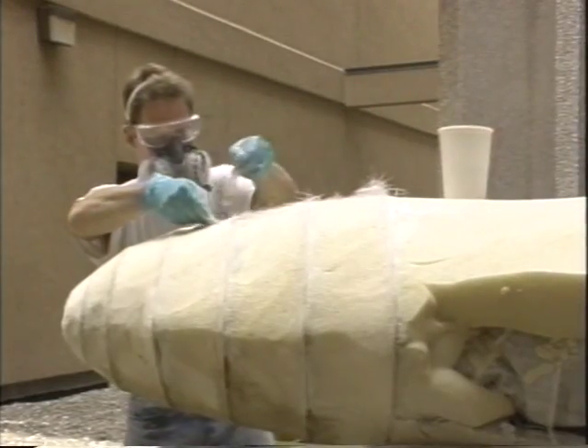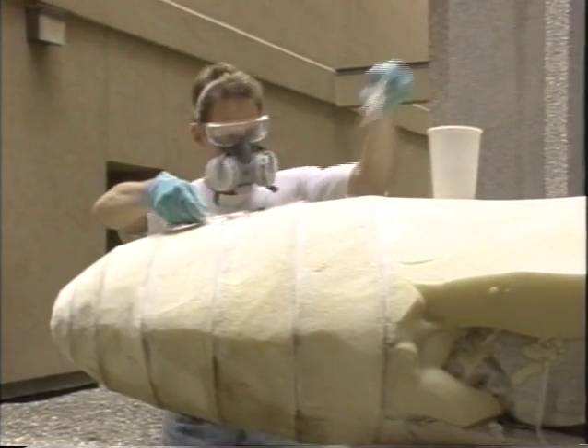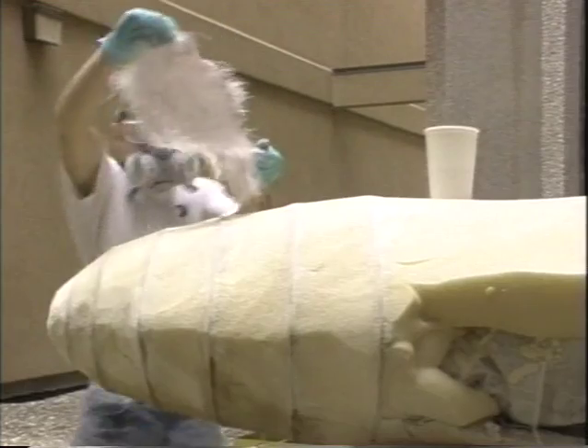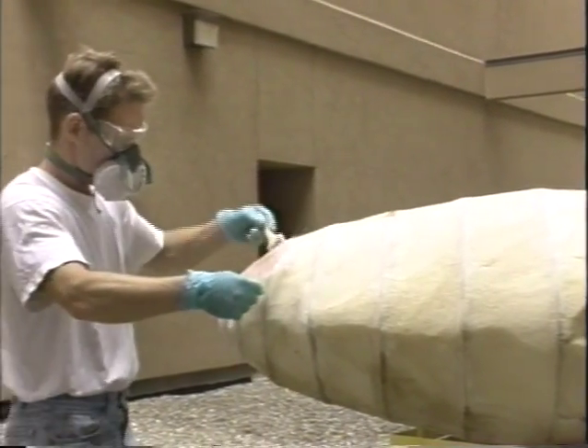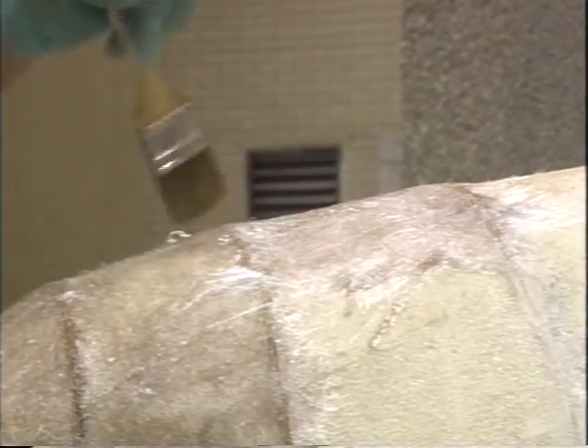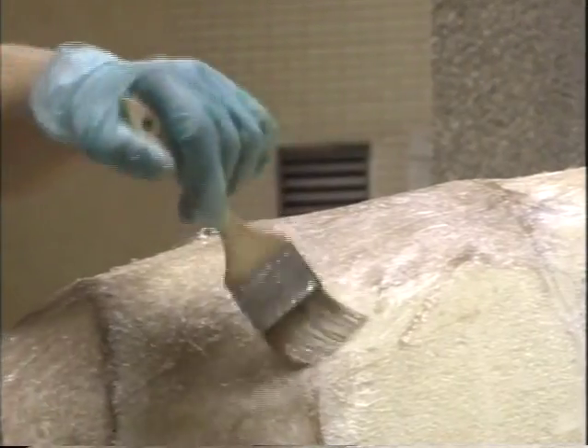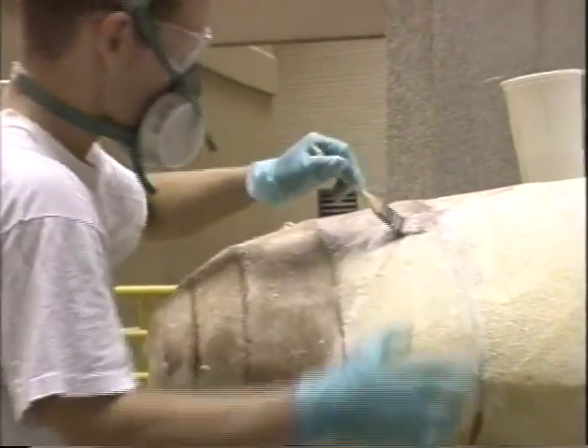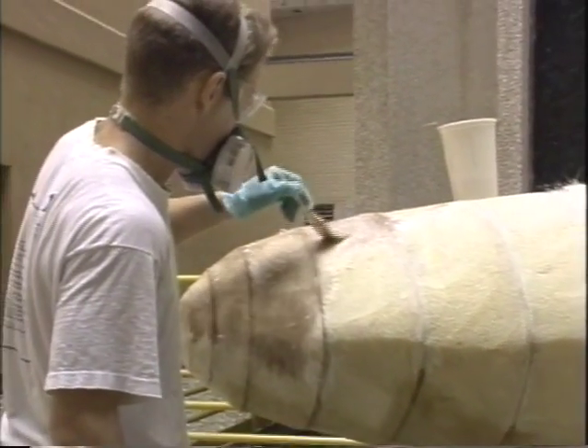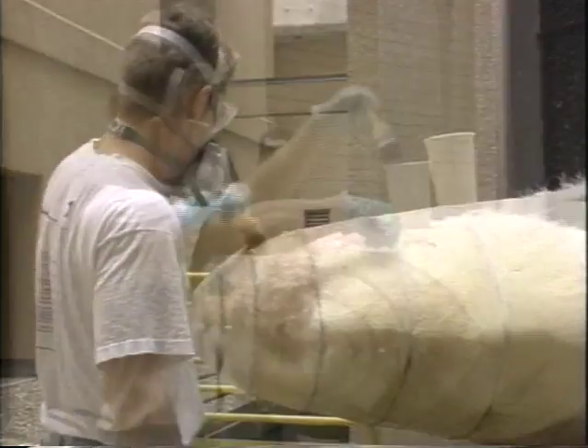Thoroughly saturate pieces of fiberglass mat, then lay them in place. Begin with torn chunks, which approximate the space between the bulkheads you are going to fill. It may be helpful to paint some resin over the foam before applying it in order to fill many of the tiny holes. The foam holds quite a bit of air because the cells were cut open during the shaping process. Try to work out the larger air pockets by stippling with a brush or wiping with your gloved fingers. A grooved saturation roller also helps to remove the air.